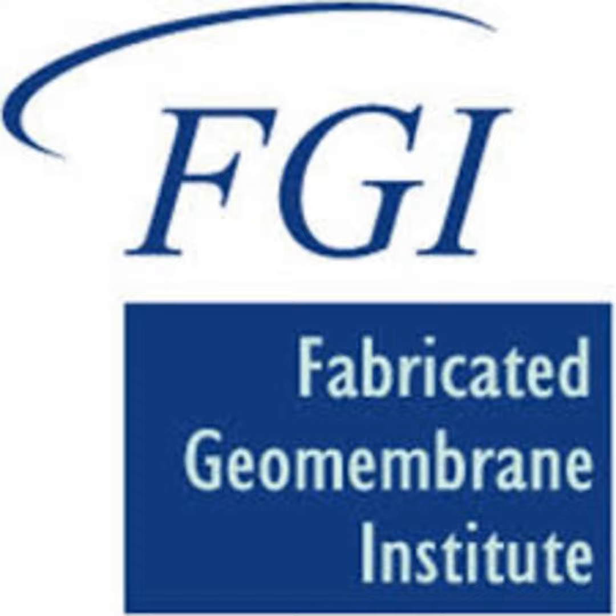For heap leach design that incorporates these materials, you want to understand the materials that you're using, the properties of them, and look carefully at the shear behavior of the test data that you're getting, and also inspect those specimens post-shearing so you can identify when the transition occurred from interface at lower normal stresses to internal in the GCL at higher, to be able to determine that normal stress. But definitely it's not a single number, and it's dependent on the materials.